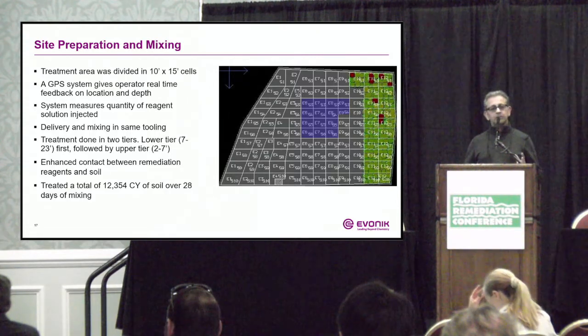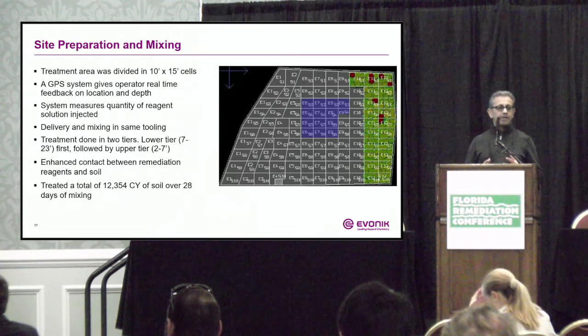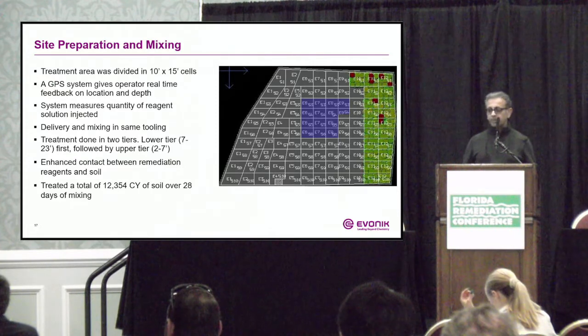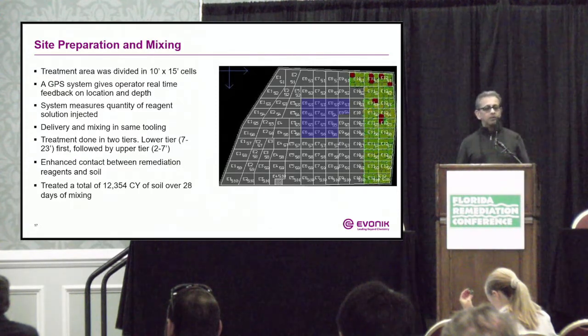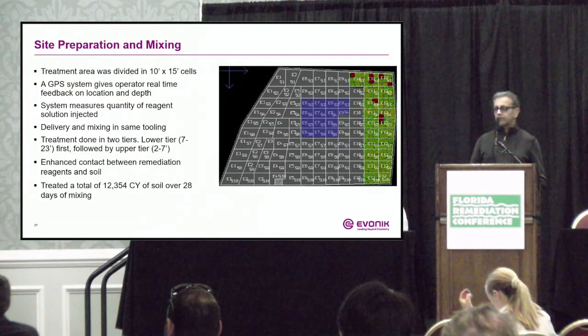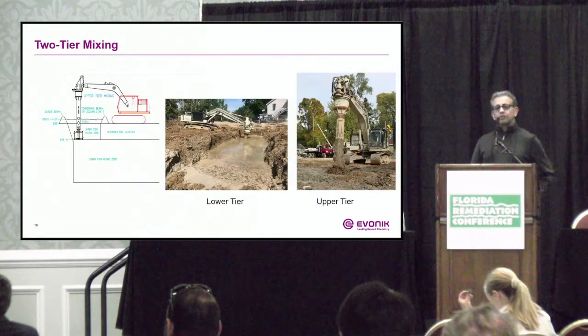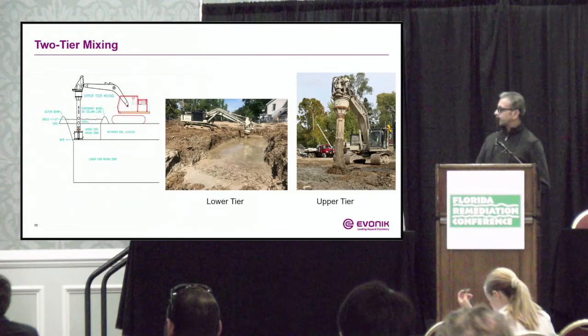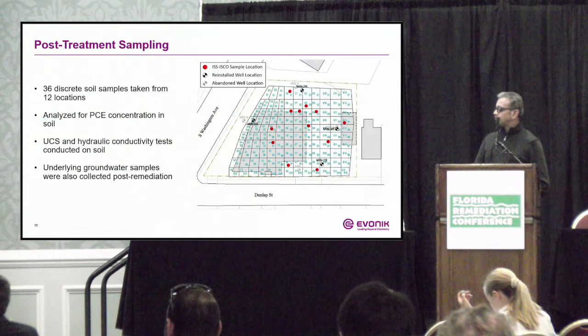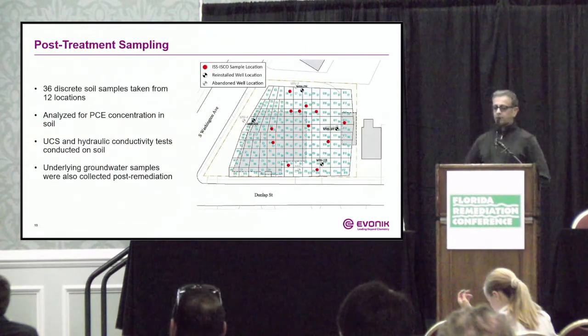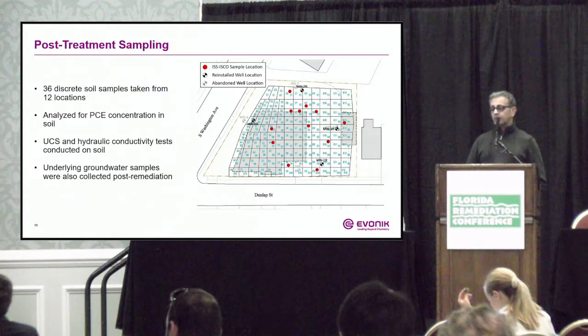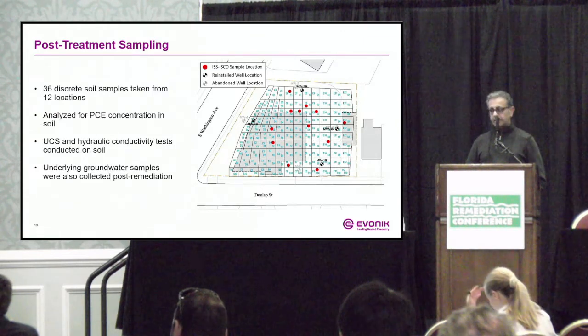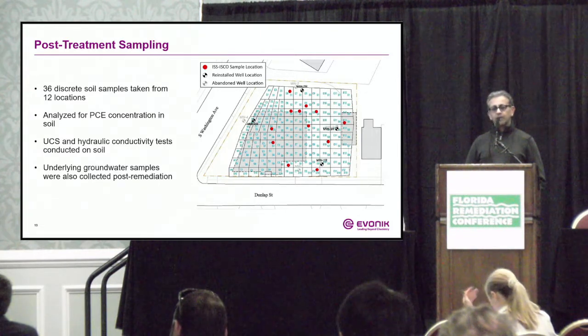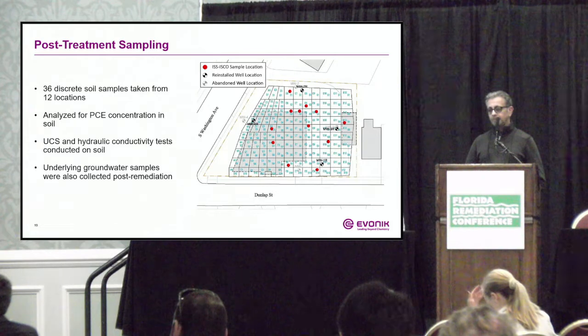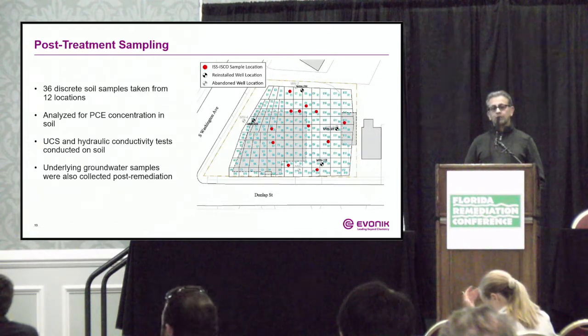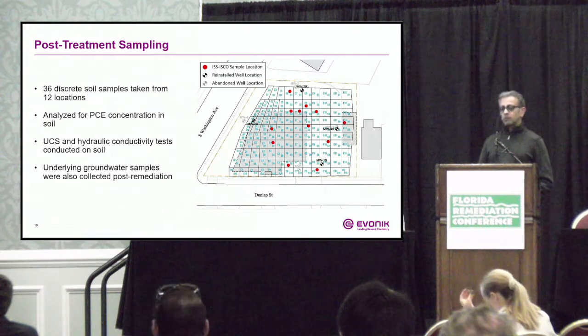The whole process made sure that there was enhanced contact between the contaminated soil and the reagents being mixed. About 12,400 cubic yards of soil was treated over a 28-day period. Here are some pictures of the lower tier mixing and the upper tier mixing. Post-treatment sampling was done, and about 36 discrete samples were collected from 12 different locations and analyzed for PCE, UCS (the unconfined compressive strength), and hydraulic conductivity. Underlying groundwater samples were also collected to see what the effect was on groundwater concentrations.